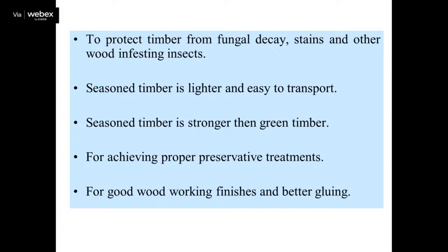Wood, when it absorbs moisture, creates favorable conditions for microorganisms and insects so that they can utilize the cellulose, hemicellulose and lignin present inside the wood, along with the starch, as their food material. And there are chances that a product which is not properly seasoned may be degraded because of this lack of seasoning. Seasoned timber is of course easy to transport. It is stronger than green timber, and it also receives preservative treatment better, as proper retention of the preservatives happens when seasoned timbers are used. And the woodworking and finishing qualities are better in seasoned timber.